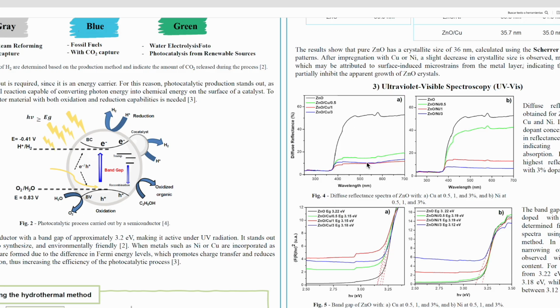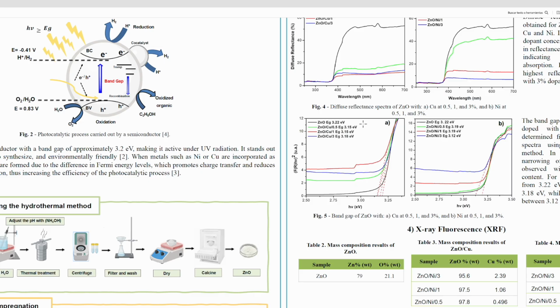We can also see that as the material is impregnated, the reflectance changes. When 0.5% copper is impregnated, it reflects less energy, so it is absorbing more. We can also see a more pronounced drop in the zinc oxide. This means that even though the reflectance is being modified, we are still within this ultraviolet energy range, since the amount of metal is too small to cause a significant change. The same thing happens with nickel, where we see the same trend at 0.5, 1, and 3%, in which the material reflects accordingly.